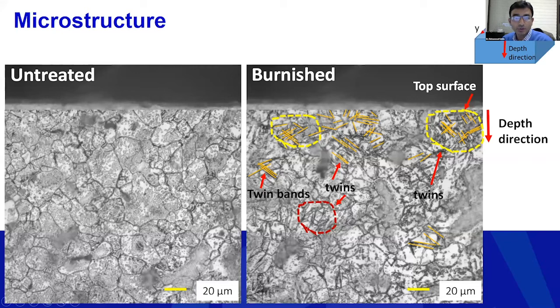These twins or twin bands could be generated because of the burnishing process, and we expect that this kind of microstructure change, forming twins or twin bands, is going to increase the surface activation energy on the top surface of the magnesium alloy. That is going to enable the HA coating to be deposited much more effectively onto the surface. So that was the hypothesis we have been looking into here: why the HA coating was much denser in the case of the burnished surface.